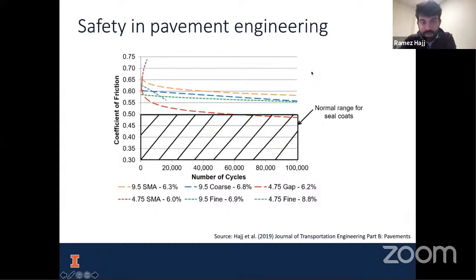So we did recommend that this is one great option for agencies to implement, is to use this ultra thin overlay, which is just a ½ inch of asphalt mix. So it's not too expensive, not too much contributing to sustainability issues, but it is quite a good option in the case, as I mentioned, that you need to replace seal coats and restore that surface friction properties. Again, you can see coefficient of friction higher than 0.55 is pretty good from an asphalt safety perspective.